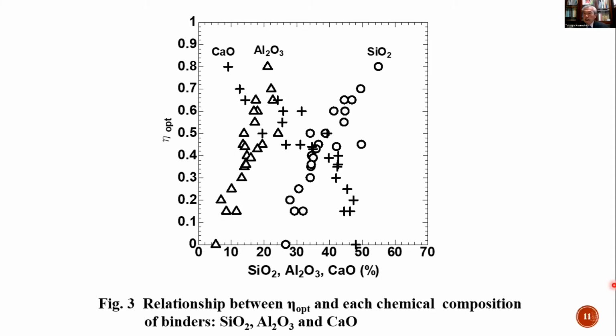Fig 3 shows the relationship between ηopt and each chemical composition of binders. Circles are for SiO2, triangles are for Al2O3, and plus marks are for CaO. In the case of Al2O3 and SiO2, ηopt is in proportion to each chemical composition, like this. But in the case of CaO, ηopt is in inverse proportion to CaO.